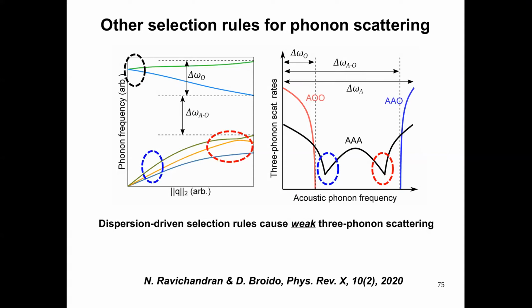Sorry, can you repeat the last sentence again? So in any material where we find a strong effect of 4 phonon scattering in strongly bonded materials like 3,5 compounds, we always find a weak 3 phonon phase space. Okay. So the lowest order scattering is weak because of some features in the dispersion and joint density of states. Okay. And 4 phonon scattering, just because of sheer combinatorics, does not get affected by the features of the dispersion. Yeah. So whenever you have, for example, a large mass ratio, you have a large AO gap that basically removes one channel, AAO, that is 2 acoustic and 1 optic channel, and that exposes other features in the dispersion. So eventually you get very weak 3 phonon scattering rates, and then 4 phonon scattering becomes comparable.